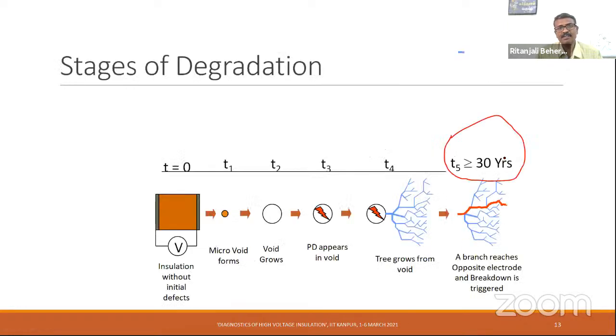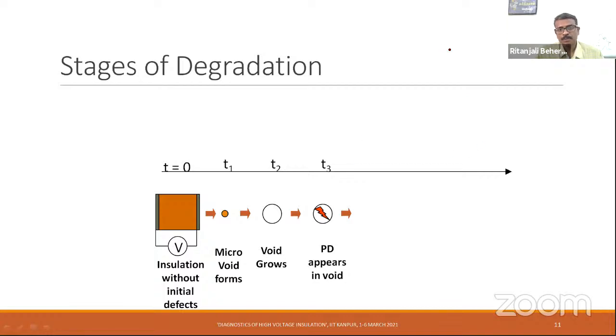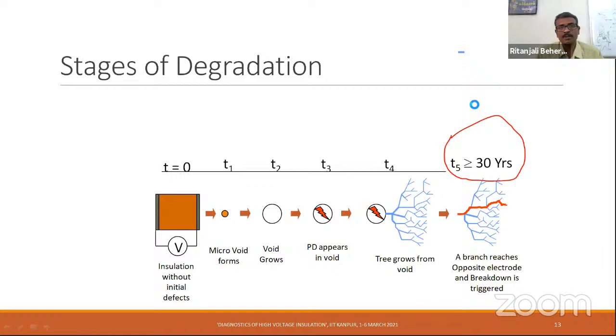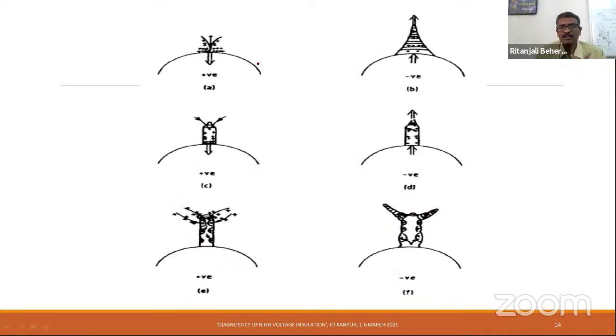But that was the case when we had a plane-plane electrode. However, if there is a rod-plane electrode or a point-plane electrode, then at the tip, this region is a highly divergent field. The temperature increases in the highly divergent field as electrons impinge and accumulate at the tip constantly, and this electron impingement would begin to break the polymer chain, which means a chemical degradation takes place in the first place.